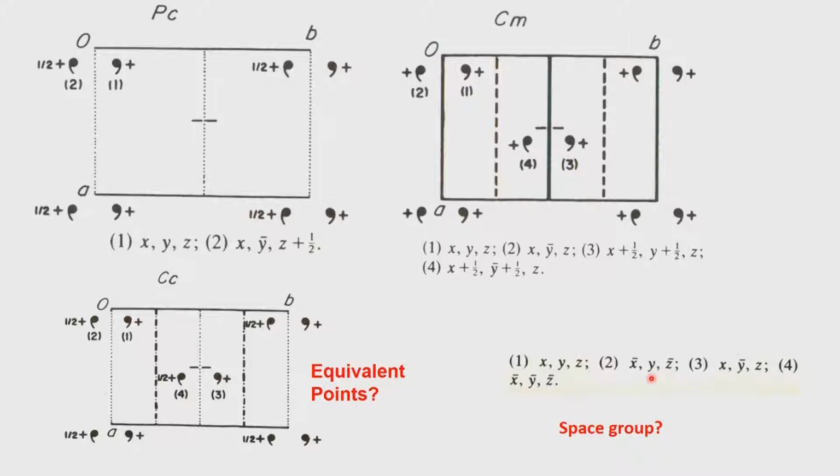So, that means that the centering is not seen. Generally, since the monoclinic symmetry is C centered, you should have equivalent points half plus x half plus y, and since that is not appearing, this is a primitive lattice. So, the first conclusion is to examine the equivalent points, find out if there are any half translations associated with x or y, or in this particular example of a monoclinic symmetry, and then you conclude that it is a primitive lattice. So, we have found that it is a primitive lattice, it has a two-fold symmetry.